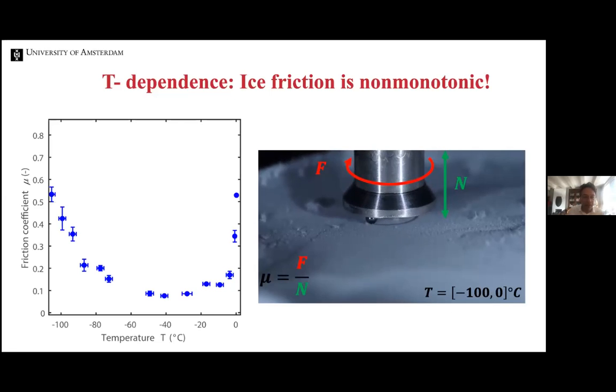Then if you increase the temperature, you go to lower and lower friction coefficient. And then right around here, you go below 0.1, and below 0.1 is really very slippery. So this is the range where ice is slippery. But then if you go too close to melting, it actually goes up again. And so this is really already a very interesting finding that we need to try and completely understand before we can say anything sensible about the mechanism of the slipperiness of ice.